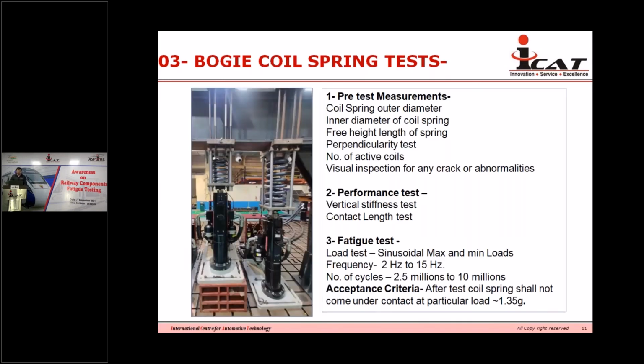And another is we recently conducted tests on railway springs. These are primary and secondary springs. These are our customized setups, and we conduct this testing for railways and their suppliers. So we need to check three tests. First is pre-test measurement: after receiving the sample, we check the coil spring outer diameter, inner diameter, free height or length of the spring, then perpendicularity of the spring, number of active coils, and visual inspection for any kind of cracks or abnormality.